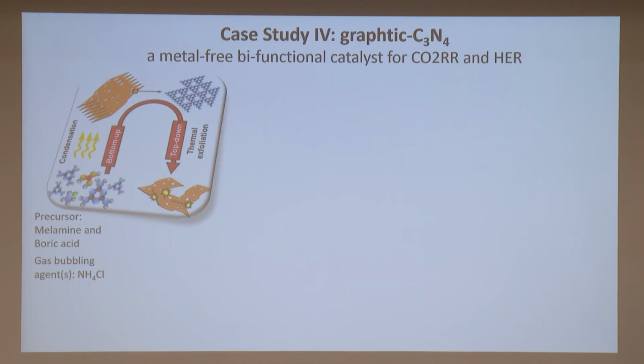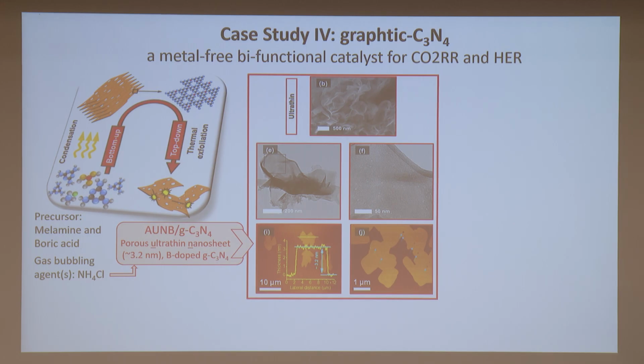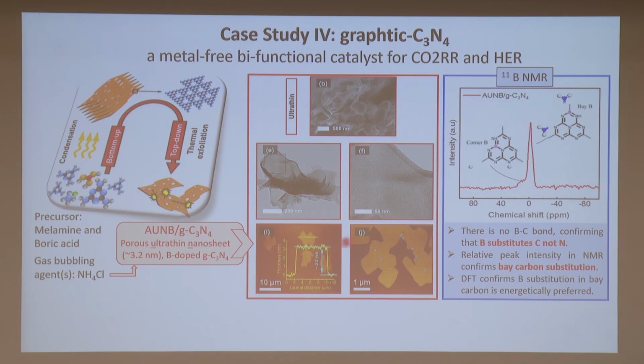And I also like to say that all such study, making material, utilizing spectroscopy, microscopy to understand at the atomic level is very important. And let's see quickly the graphitic carbon nitride that we make in such a case. This is by the chemist method, solution-based. So we start with the precursor melamine for the carbon nitride and add boron, and then also add a gas bubbling agent to make a very thin sheet. And for the graphitic carbon nitride, we have difficulty making a good TEM image, but we also have another powerful tool, the NMR tool. Utilizing the NMR tool, we can specify where the boron goes, and prove incorporation of boron effectively. In this case, we proved it's in the bay carbon. Okay, the stronger signal indicates the bay carbon.